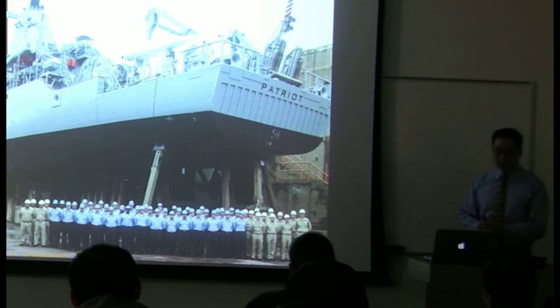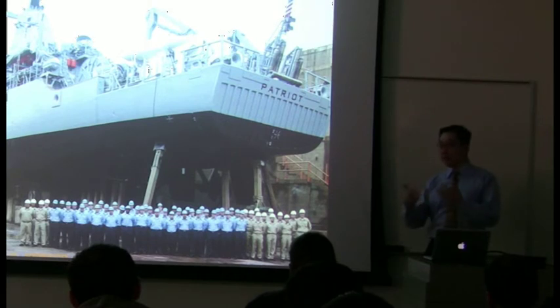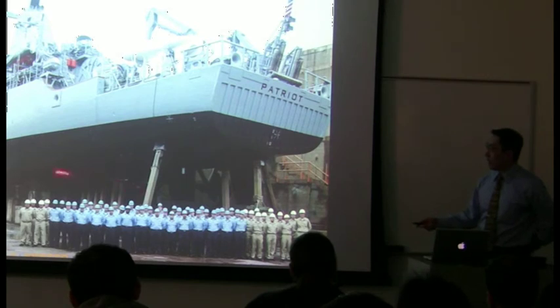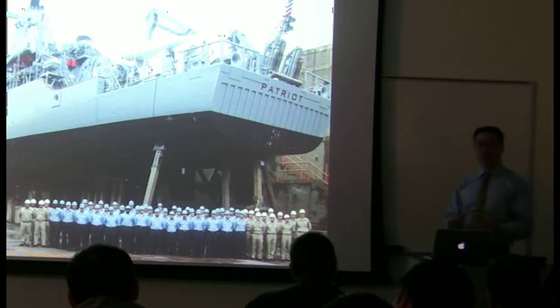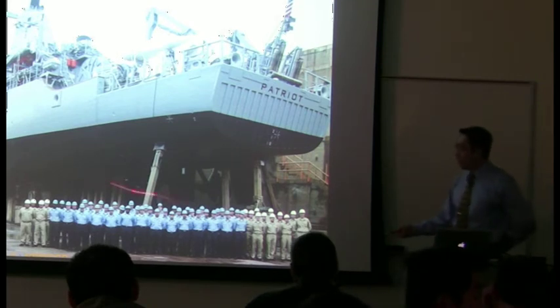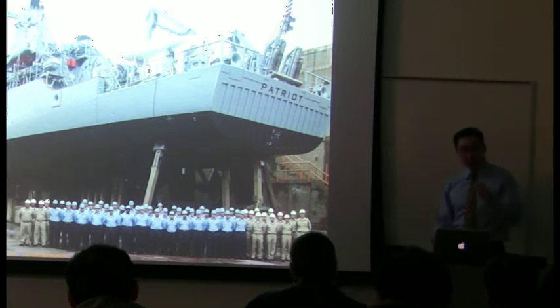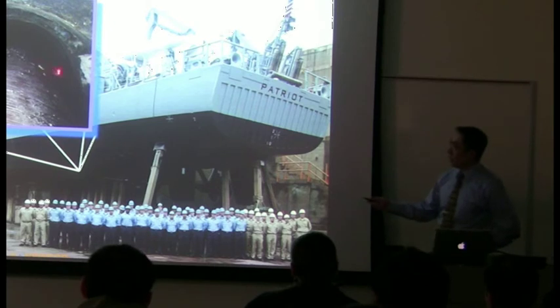And due to reasons relating to these ships, a lot of the new mines can be triggered by magnetic field. Because of that, the Navy does not use steel shafts. They use hollow nickel aluminum bronze shafts. This is a long, hollow cylinder. By being a soft material, it's prone to wear, and the wear occurs at the bearing regions.